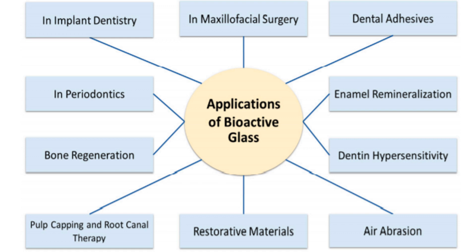Another use for bioactive glass is in restorative dentistry. The main issue with mainstream restorative materials today is their polymerization shrinkage upon application, which decreases marginal integrity and accelerates the formation of secondary caries. However, the bioactive properties of bioactive glass and its ability to remineralize enamel and deposit apatite prove essential for achieving the perfect restorative material. For example, fluoride-impregnated bioactive glass was found not only to increase remineralization but also to reduce enzymatic degradation of the dentine collagen network.